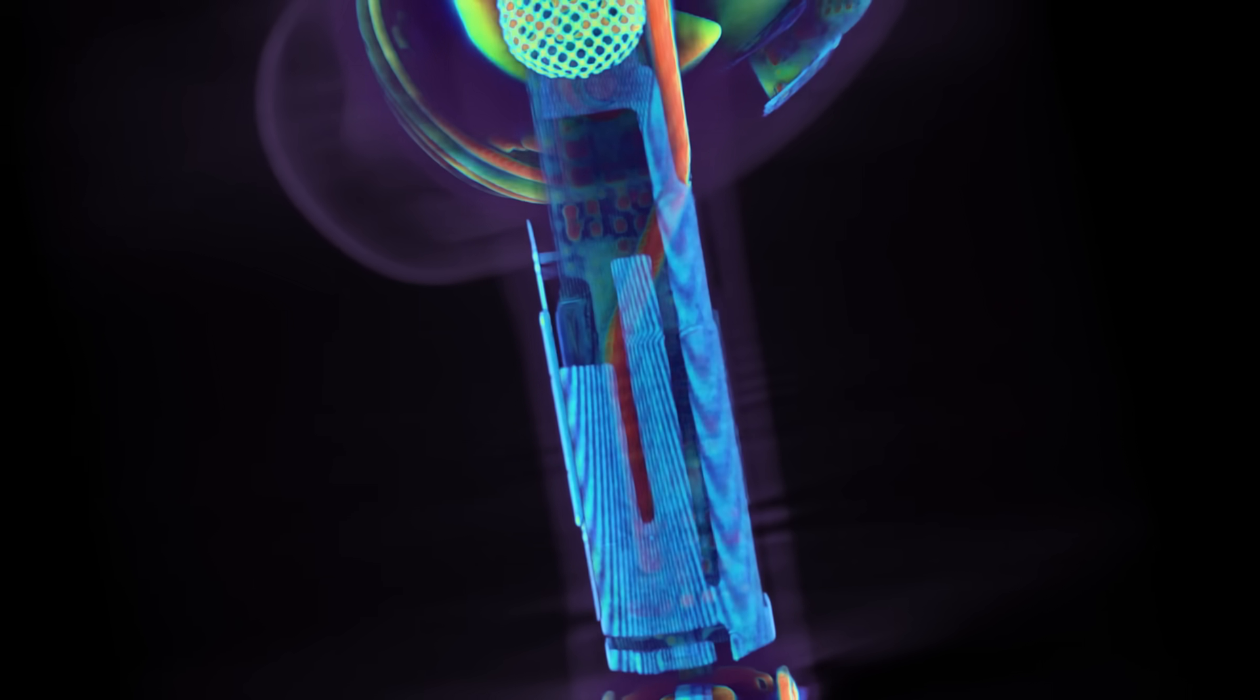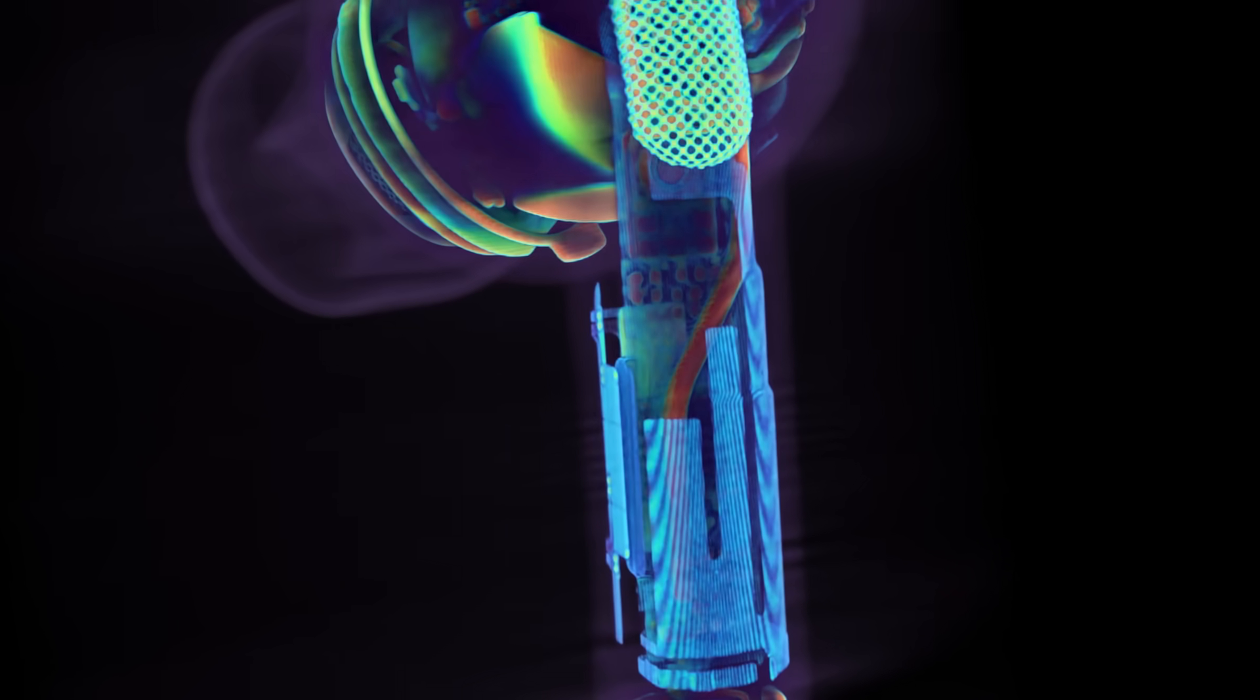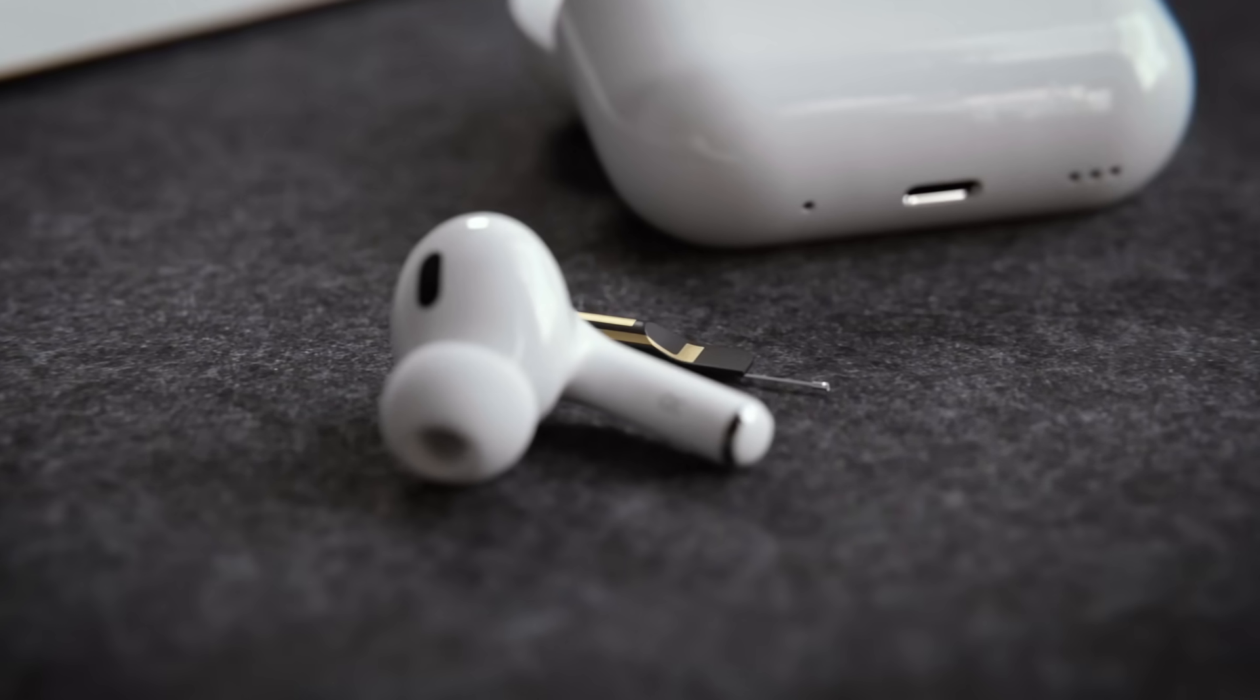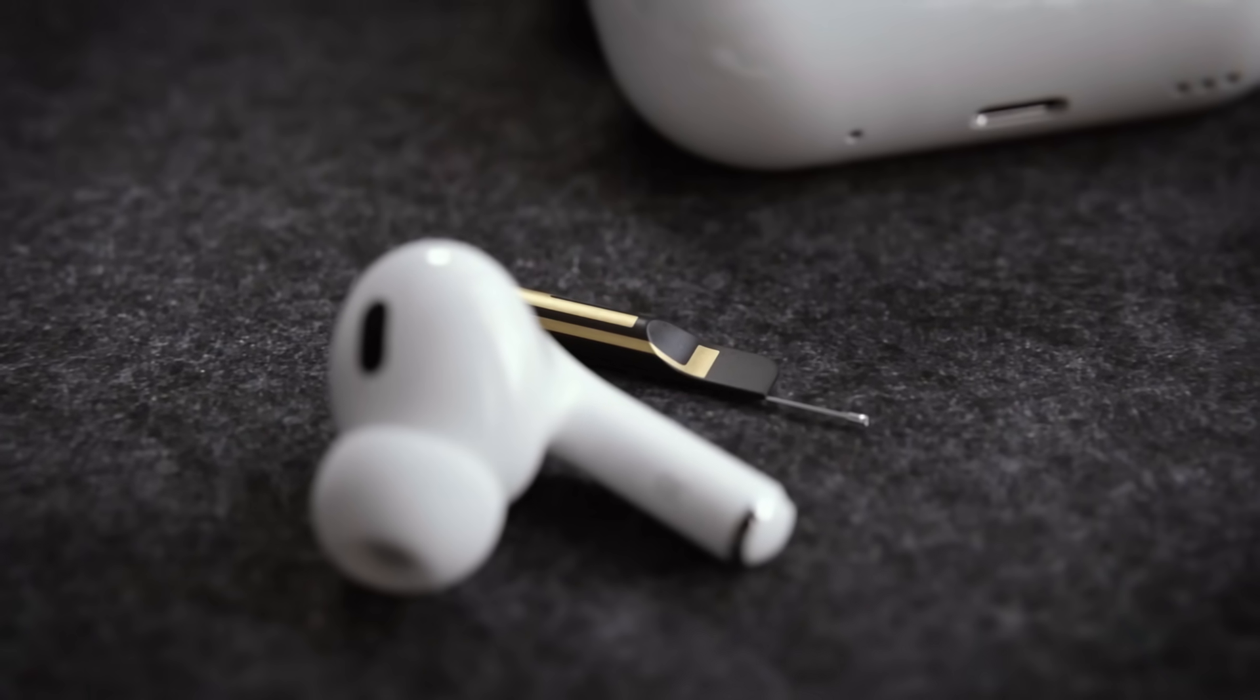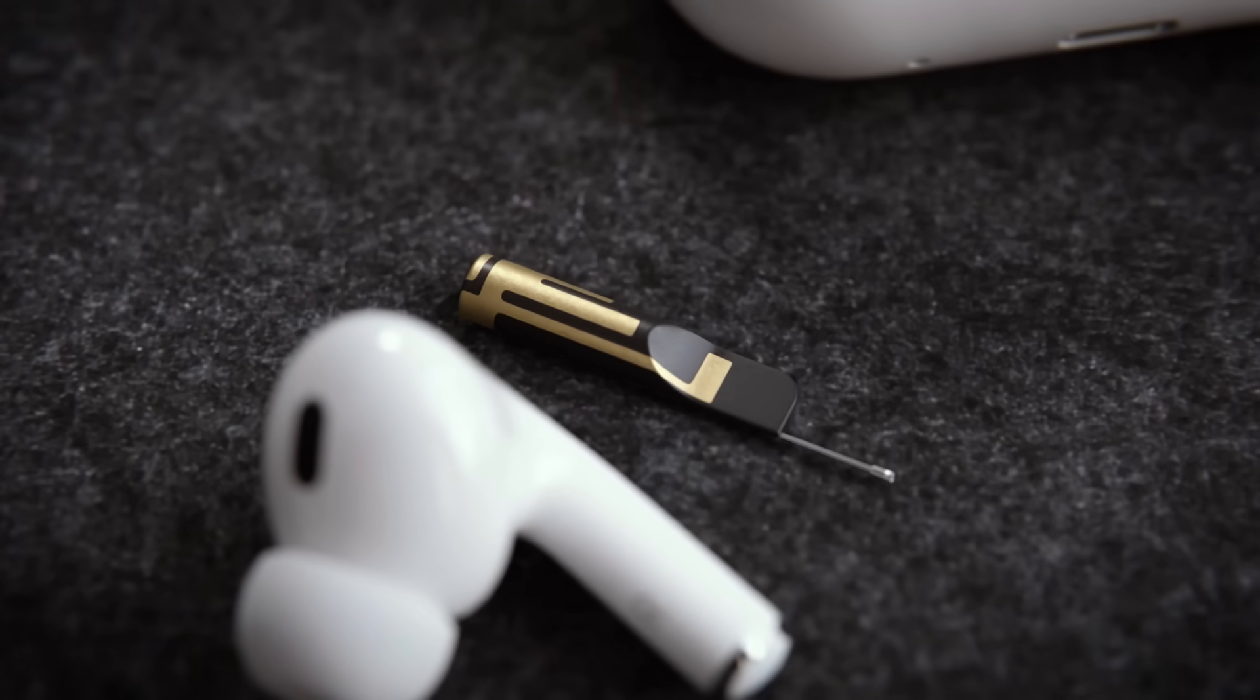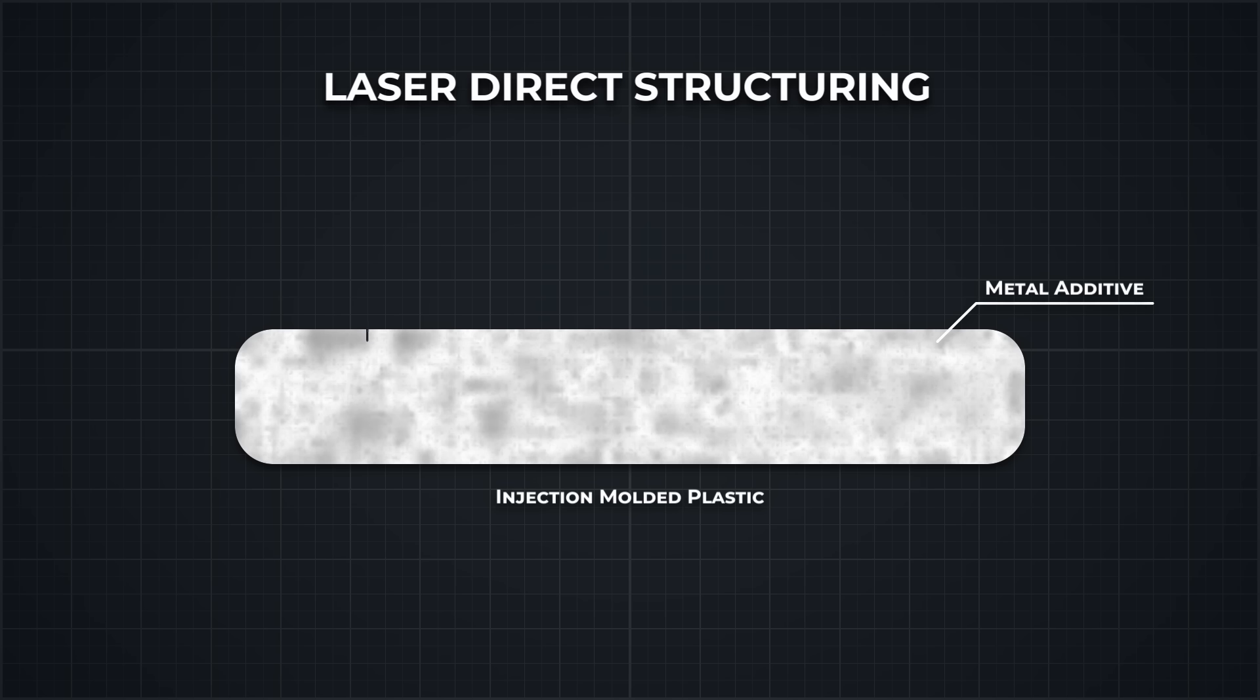They embedded the antenna onto the surface of an injection molded plastic cylinder. If you open an AirPod, you'll see this black plastic part, and the metal antenna is perfectly molded onto it, following its complex surface like it was painted on. The secret is in the plastic. It has a small amount of metal added to it. A laser can then engrave the exact shape of the antenna into small channels with a rough surface that exposes the additive.